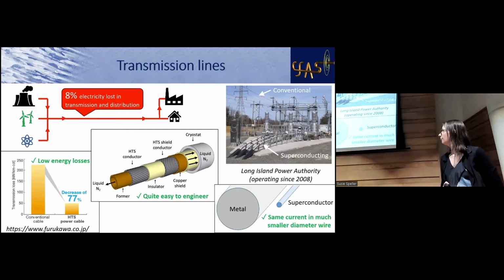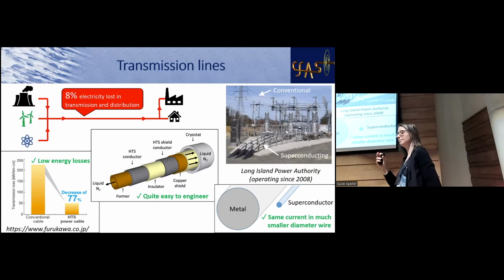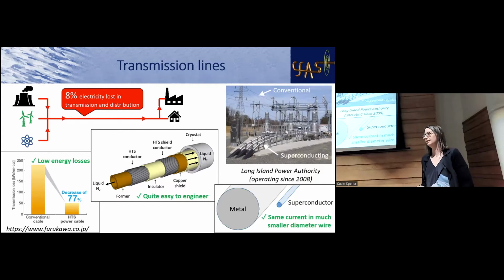And then, as I mentioned before, we can get a lot more current down the same amount of material. So we can get about 100 to 150 times as much current to the same cross section, which means that here, this is a demonstrator that was built at Long Island some time ago now, and these are the superconducting cables, and they carry as much power as all of those overhead ones do. So you can get the same amount of electricity in a much smaller space. And that might be beneficial in places like Tokyo, which are very difficult to get new power cables and underground power cables. You could replace your conventional underground cable with a superconducting one, which carries much more current.